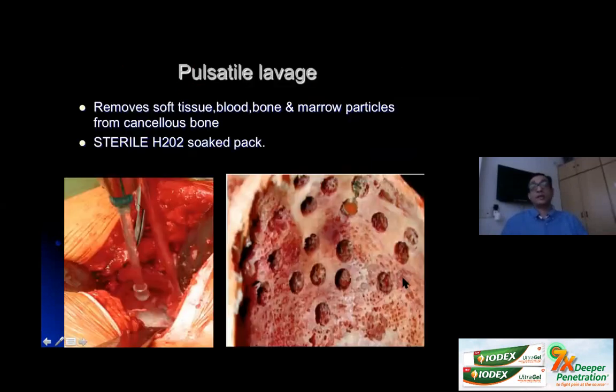The next step would be to give a nice pulsatile lavage. So take a pulsatile lavage, give a thorough lavage, and remove all the soft tissue, bone, blood, and marrow particles from the cancellous bone. After that, once you achieve this stable and dry bed of bone, you can pack it with a sterile hydrogen peroxide soak, so as to maintain this dry bed for you to cement well.